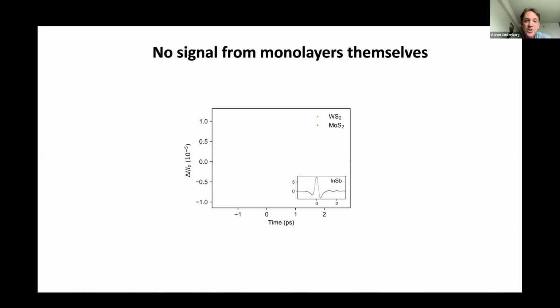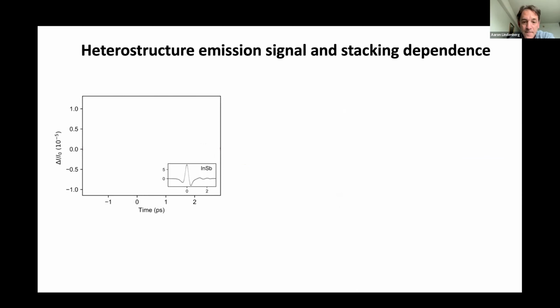And so here are some simple experimental results, which show what we actually measure. The first thing you can do as a control is measure a signal from a pure monolayer, so a pure MoS2, for example, or a pure WS2. If you do that, then essentially you measure nothing. There are some very weak signals, even for the monolayers, I would say. But to first order, the response is essentially negligible for the monolayer. However, when you form a heterojunction, a bilayer, so this is now MoS2 on WS2, you get a very clear time-dependent signal.